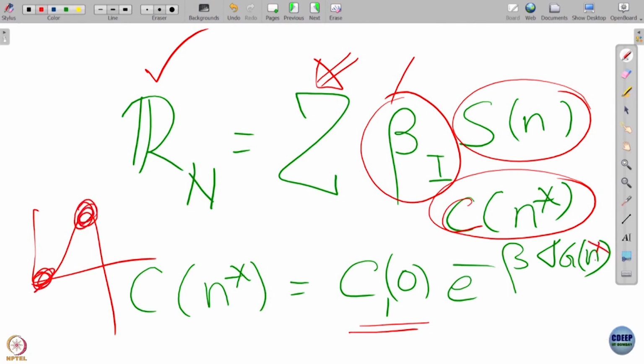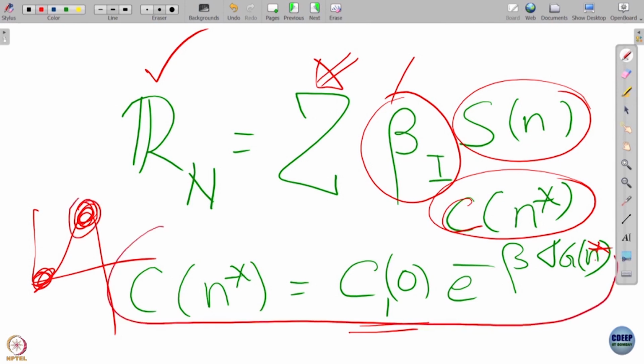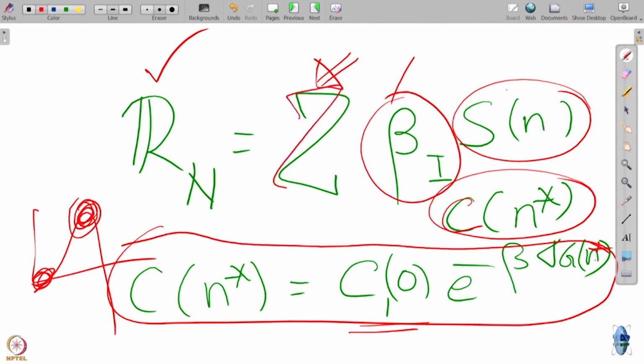So that is given by n star, my probability of being here is given by this expression, and my impingement surface is giving that, and this Zeldovich factor is called the non-equilibrium effect that takes into account going both ways. This is exactly what we do in chemical kinetics, we sometimes call that the Smoluchowski equation approach. And all these things happen at a very similar time, and it is exactly Kramers' theory also of chemical kinetics, a very well known theory of chemical kinetics that we will do a little bit, hopefully, someday.